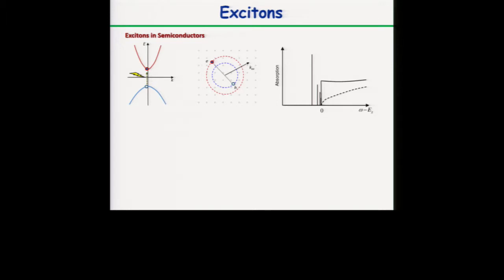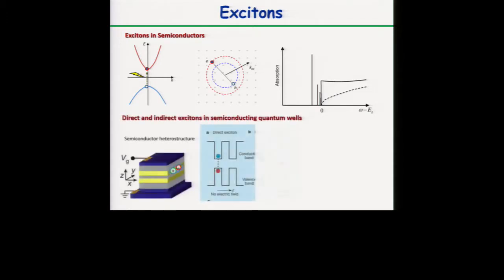As I say, in these TMDC semiconductors, we shine light. We can create an electron-hole pair, which are bound by Coulomb interaction. Once we knock out an electron from the valence band, it goes to the conduction band, and then they form this exciton, this electron-hole pair, right? They usually live short because they are aligned in momentum, so they live a few picoseconds at most. That's what are called the direct excitons.